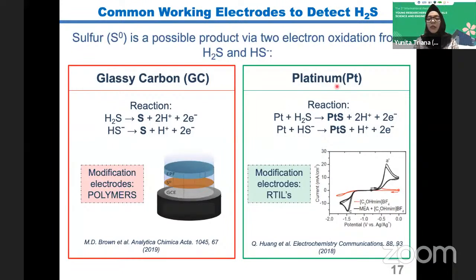And also on platinum, sulfur reacts with Pt to make PtS. So to prevent this fouling on the surface, they use an electrode modified with room temperature ionic liquid. But RTIL is organic and very dangerous for the environment in this case.